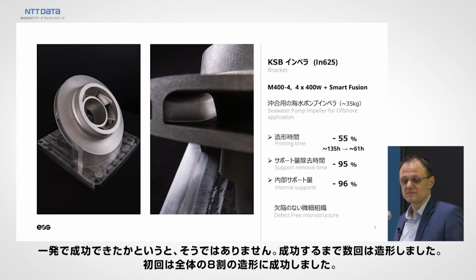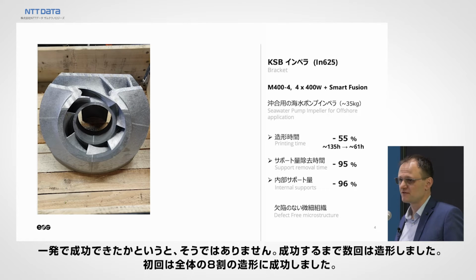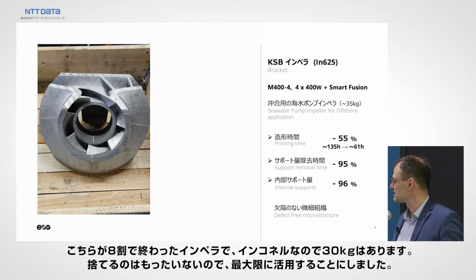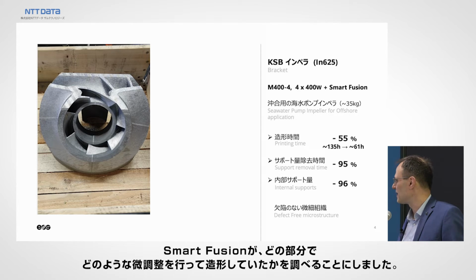So a good example. Did it work the first time? No, it did not. We needed a few iterations until this application was actually successful. And ultimately, we achieved an 80% impeller. So this 80% impeller was 30 kilograms of Inconel. So what should we do with it? Shall we just throw it away? We thought, maybe not the best idea.